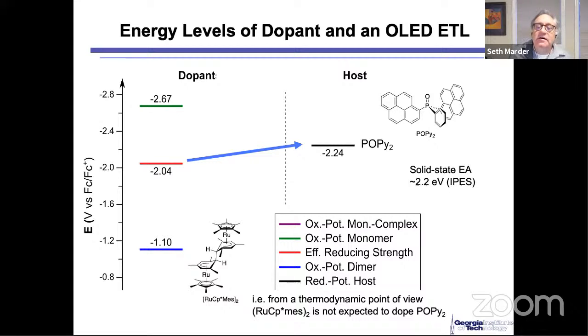I'll point out two things. I show two numbers here. One is a reduction potential versus ferrocene, and the other is a solid state electron affinity measured by IPES. The numbers are the same, but this is a reduction potential and this is an electron affinity. So here is the scoop. If we took this molecule down here and we oxidized it, that couple occurs at about negative 1.1 volts versus ferrocene. So for this to actually transfer an electron directly to here has a 1.1 volt barrier. That's not going to happen.